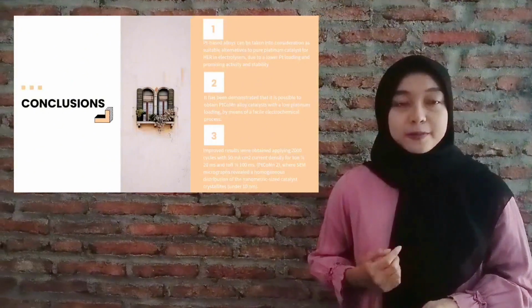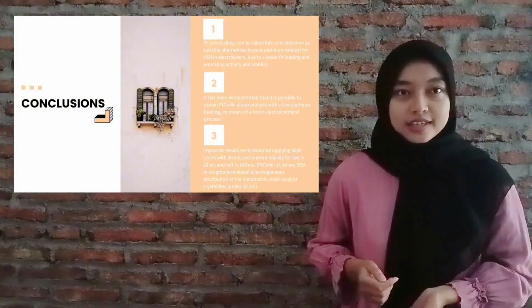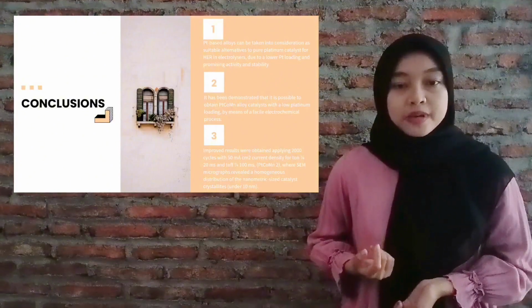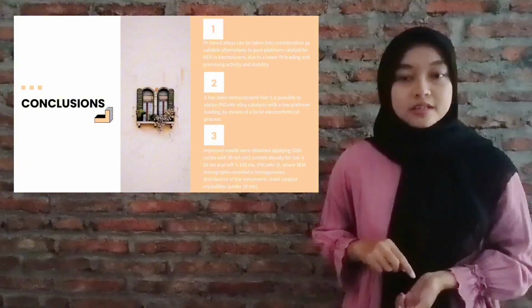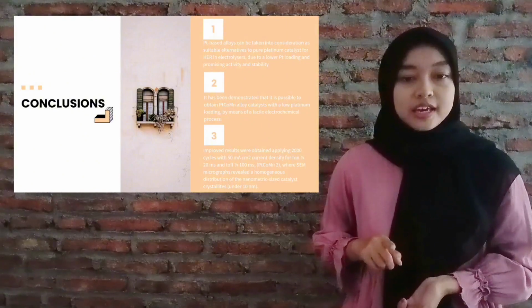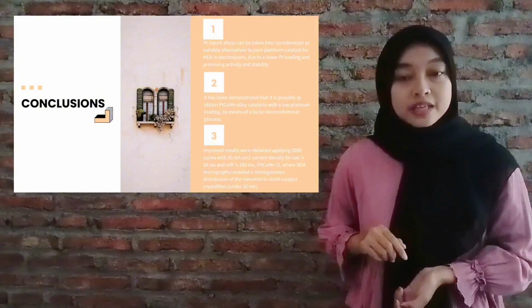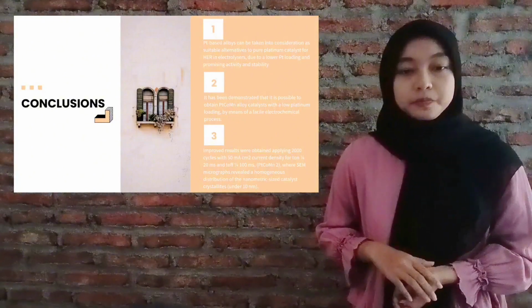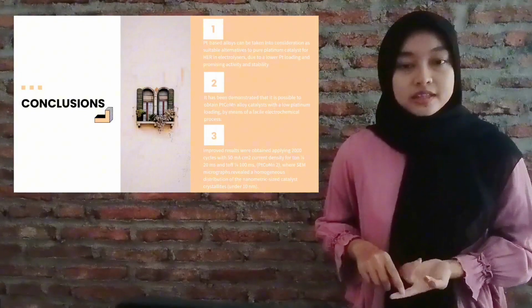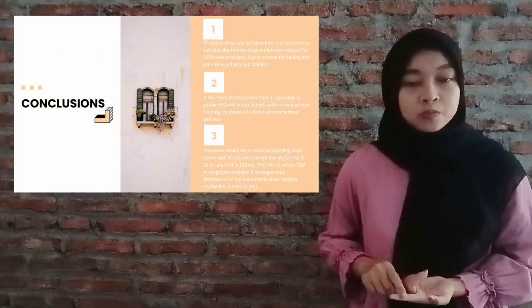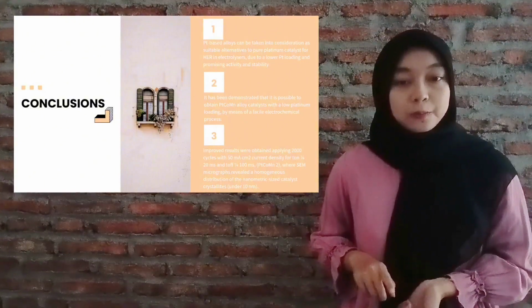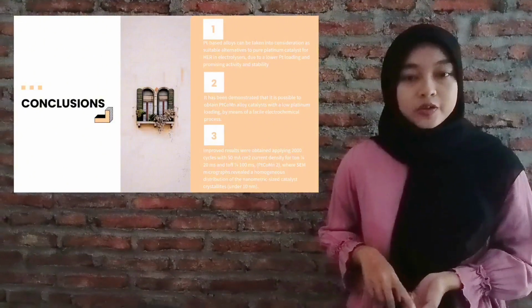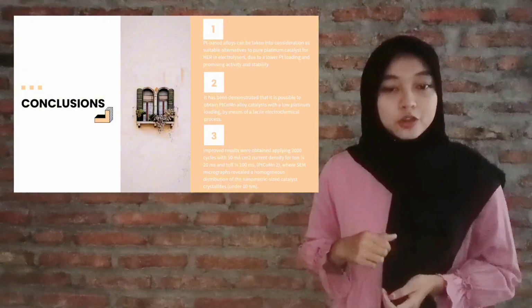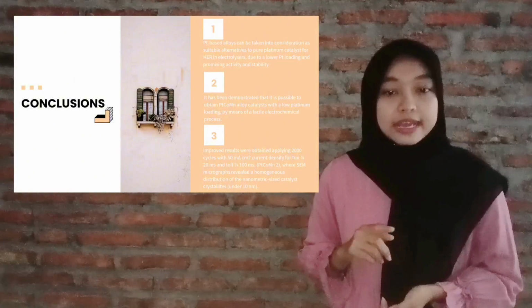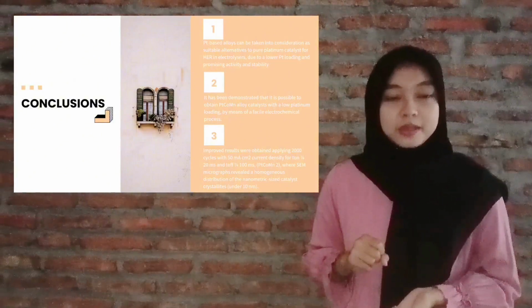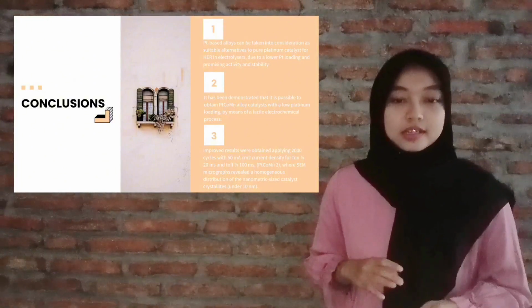Okay, next I will explain the conclusions in this journal. First, platinum-based alloys can be taken into consideration as a suitable alternative to pure platinum catalysts for HER in electrolyzers due to a lower platinum loading and promising activity and stability. Second, it has been demonstrated that it is possible to obtain platinum cobalt manganese alloy catalyst with a low platinum loading by means of a facile electrochemical process. Improved results were obtained applying 2000 cycles, where the SEM micrograph revealed a homogeneous distribution of the nanometric size catalyst crystallites.